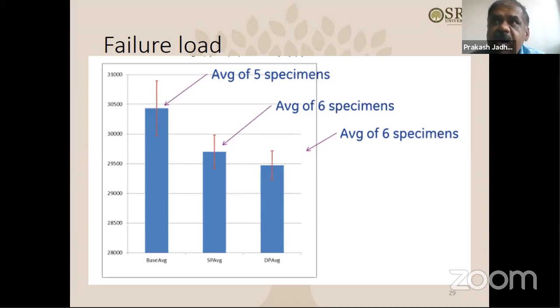As you can see here, it says the specimen is failing at 30,500. You cannot design the blade accordingly, based on this ultimate failure load. So we have to find out when the cracks are initiating. That is very, very important in the case of critical components like fan blades, where we cannot afford to have any kind of initiation. So that's why the design should be based on the initiation failure load.